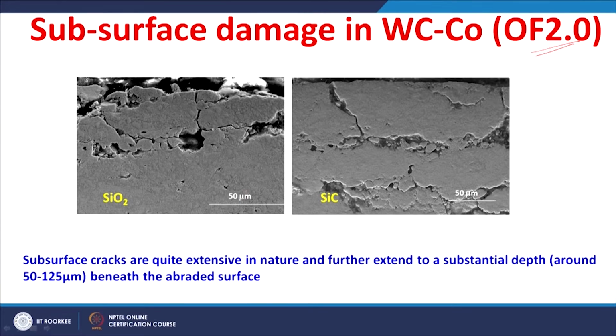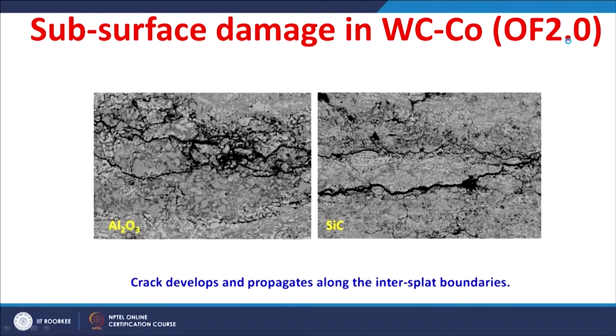The depth is around 50 to 125 micrometer. Till that depth you have a network of these subsurface cracks. So, this also indicates the severe wear occurring in the coatings done with the maximum oxygen to fuel ratio of 2.0. The crack develops and propagates along the intersplat boundaries, observed in a high magnification image of the subsurface. You can see so many cracks, they network, and then you will have severe wear happening because of this networking of cracks at the subsurface along these intersplat boundaries.